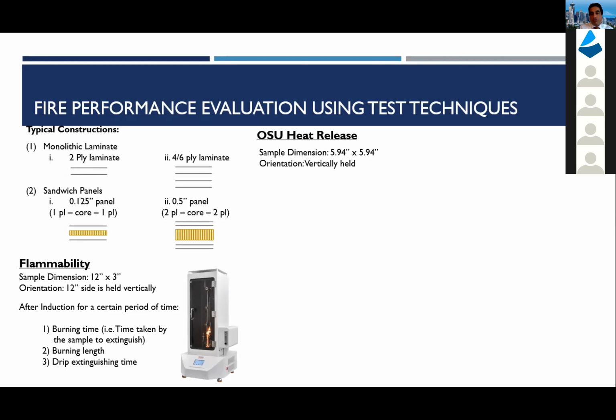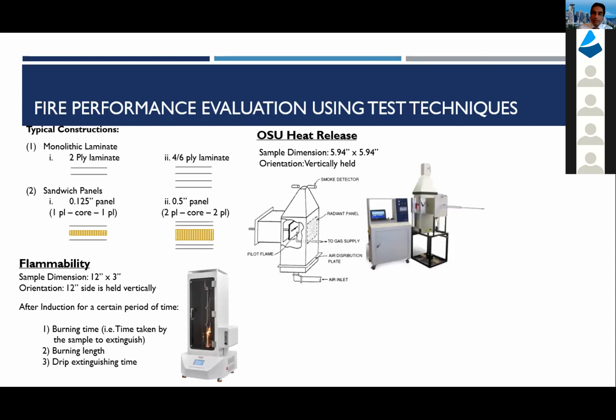Next is OSU heat release measurement. In this test, the sample dimensions are 5.94 inch by 5.94 inch, and samples are vertically held. Here is a picture of the OSU calorimeter, and the schematic on the left shows how the sample is held vertically against the radiant panel.